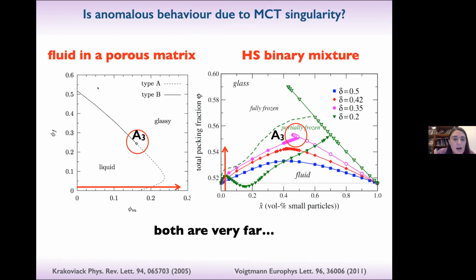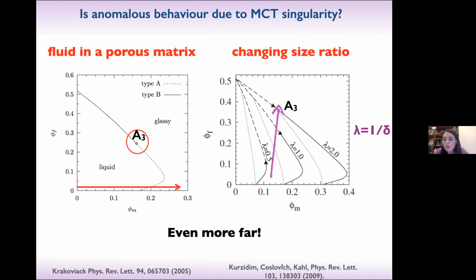Let's look also at the fluid in the porous matrix. These were the calculations of Krakoviack for equal size hard spheres, which is not our case. But luckily, in the paper by Kurzidim et al., they extended this calculation also to different size ratios, and their lambda is 1 over delta. If you change lambda, you decrease delta and go towards our critical size ratio, your A3 actually moves here, and we are here, so we are even farther away. So really, this indicates that in this case, MCT cannot help us.